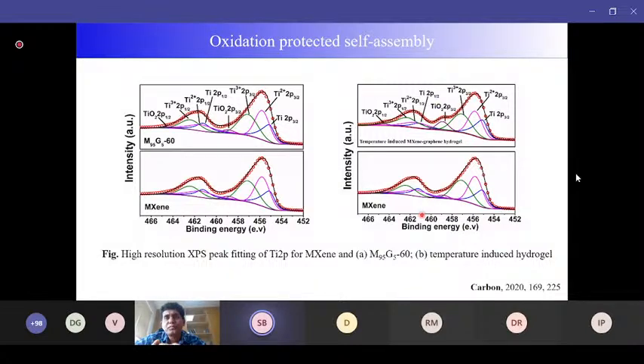that corresponds to TiO2. In the pristine MXene, which we started with, it also had some impurity phase like TiO2, but whenever you do it with a temperature-involved method, there is an oxidation and the TiO2 content increases. This TiO2 is insulating in nature, so as a result, the overall conductivity of the material decreases. However, in our case, this is the starting material MXene, but when we made it into a hydrogel, you see that the TiO2 peak remains very similar. So there is no further oxidation from this processing. So this gelation is an oxidation-protected gelation, where we can avoid the oxidation, which is very common in any thermal processing method.